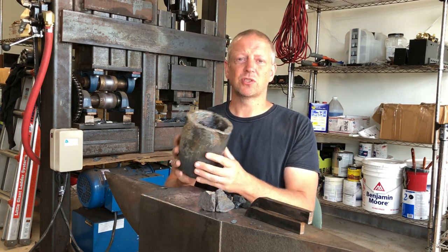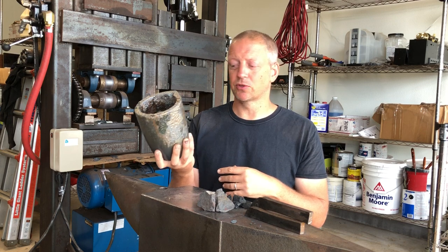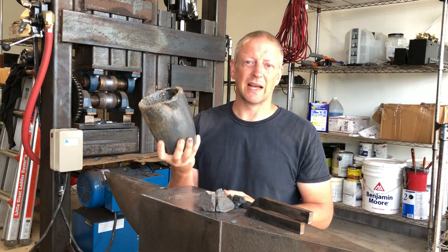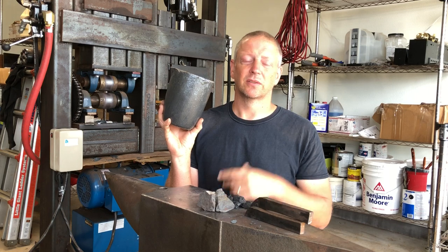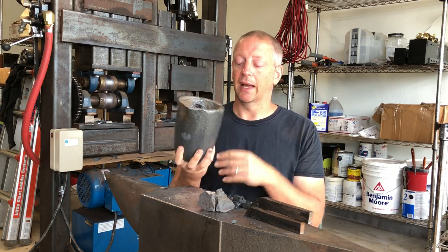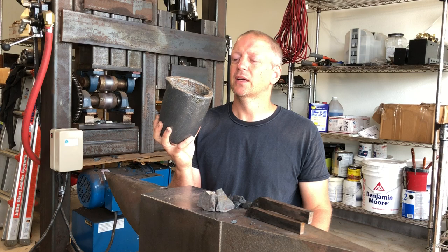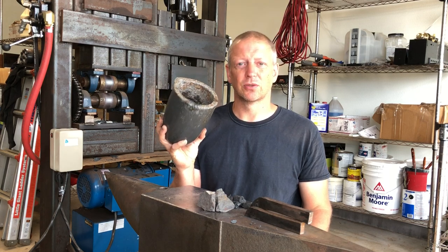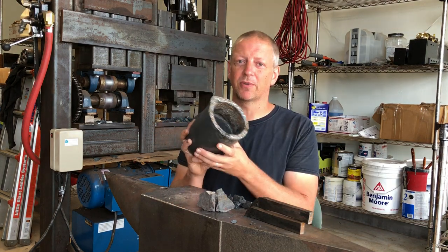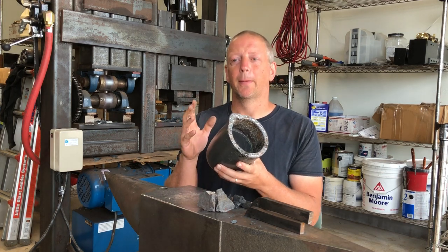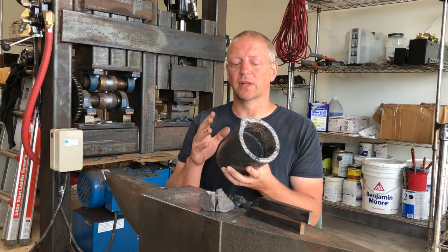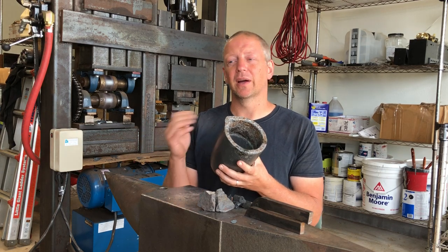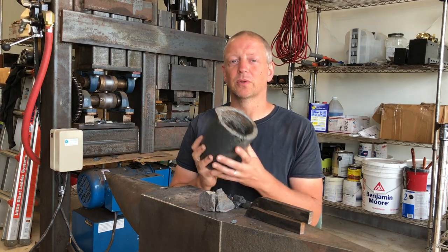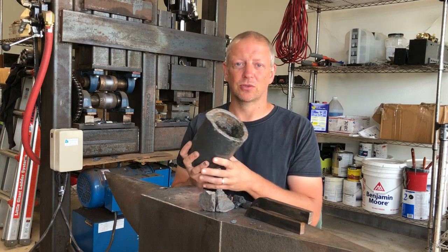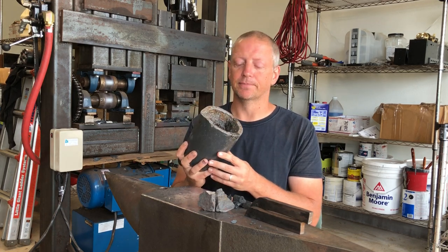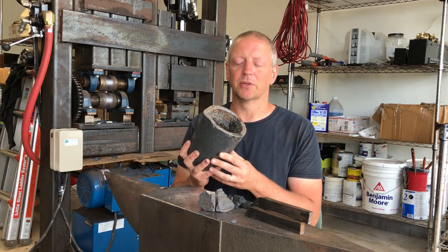So first, a lot of folks have asked me what type of crucible I use. This is a Salamander A6, which is the size and shape designation. It is a clay graphite crucible. They're sometimes referred to as just graphite crucibles, but you want to make sure that you get a clay graphite crucible rather than a straight graphite crucible. Those are out there. They are not suitable for melting iron. Iron consumes carbon pretty rapidly.